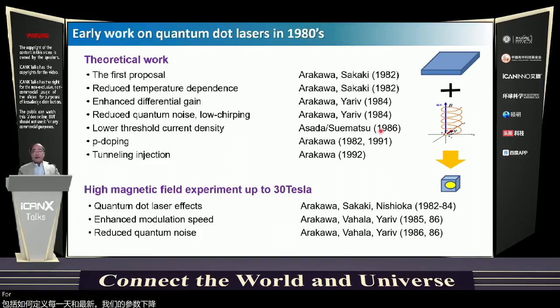For experimental simulations, we placed quantum well lasers in a high magnetic field, with which one-dimensional confinement by the quantum well potential and two-dimensional confinement by the Lorentz force are realized. Thus, we succeeded in demonstrating the quantum confinement effect in the semiconductor laser.